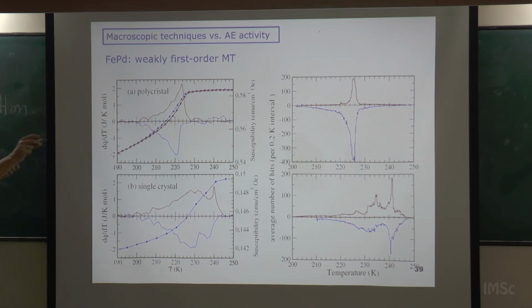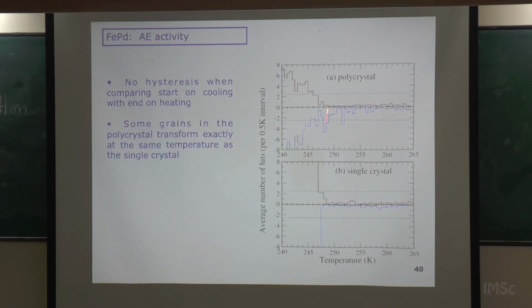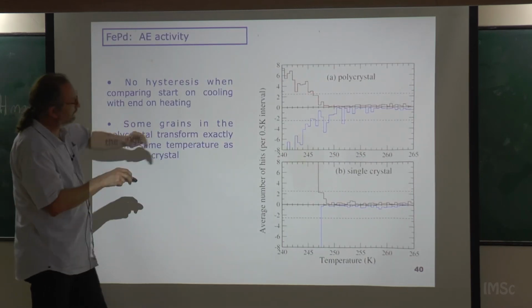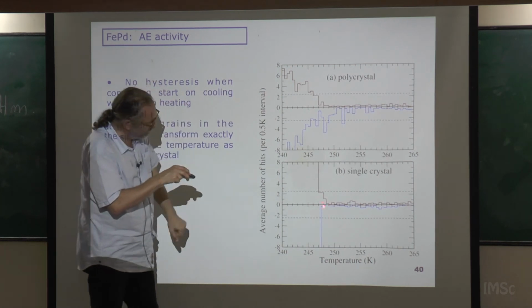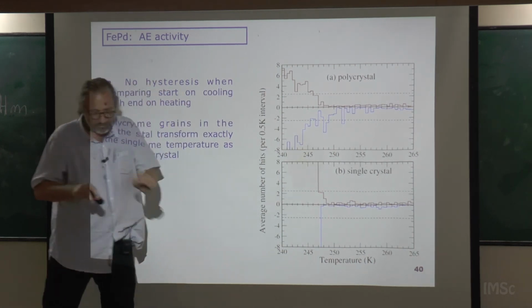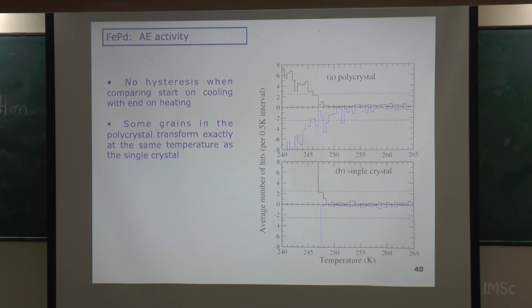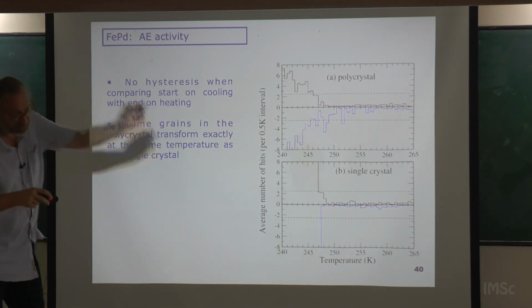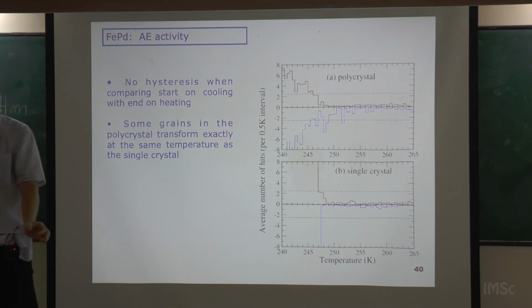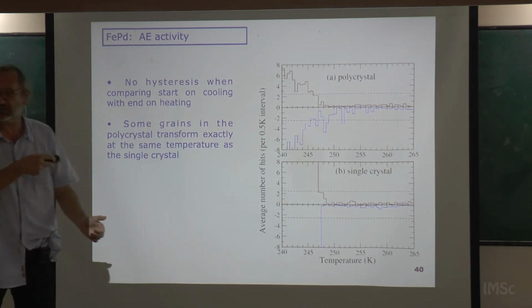When you do acoustic emission, you get enormous resolution, and you can magnify the initial part, and then you put one of these thresholds, and you see that it's not like this. So this means that when you cool, there is a moment in which a small part of the system starts to transform, and this is exactly the same as when the last domain transforms back. There is not this shift. This was what we studied.